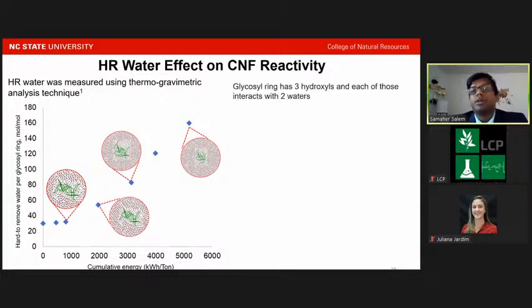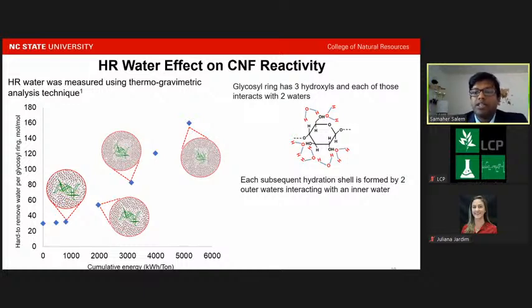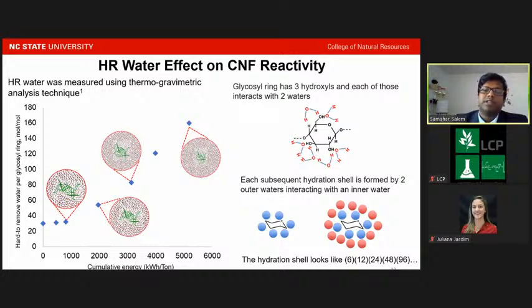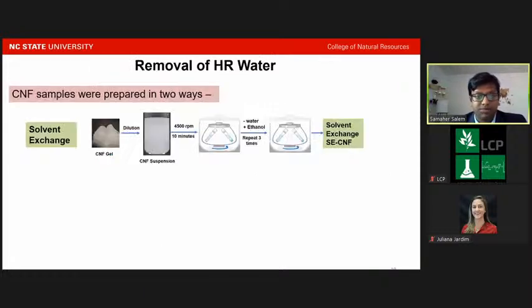So the glycosyl ring has three hydroxyl groups, and each of those can react with two waters. And each subsequent hydration shell is formed by outer two waters interacting with an inner water. That is, the six waters can interact with 12 waters, and the 12 waters will further interact with 24 waters, and further 48 waters and 96 waters, and thus it goes on. And so with the increase of the hard to remove water content and the bound water content, the hydration shell does increase, which explains why the reactivity of the nanocellulose decreases after reaching a maximum point after a certain time.